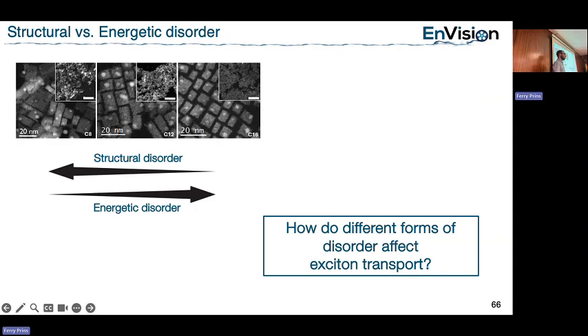Diffusion is something of a very global thing, and it doesn't reveal the details of what is behind. Of course. But these Brownian dynamics simulations are taking the energy transfer, so it's a discretized model where you don't treat it as a diffusion, you treat it as: what is my transfer rate from one particle to the next? The key there is that if there is no energetic disorder, then that individual transfer step, I'm not talking yet about how many neighbors you have, is equal moving from A to B as from B to A. If I have energetic disorder, then moving from A to B is not the same as moving from B to A, because one is downhill and the other one is uphill.